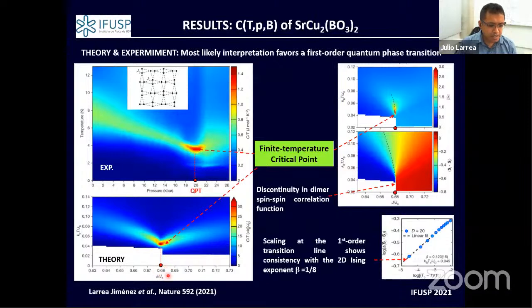This is a very important value because in many calculations, we can also see, for instance, another feature of a discontinuous phase transition, in particular because here you have an enhancement of the correlation length. Here is another color map that shows the correlation length becomes bigger at the quantum phase transition.